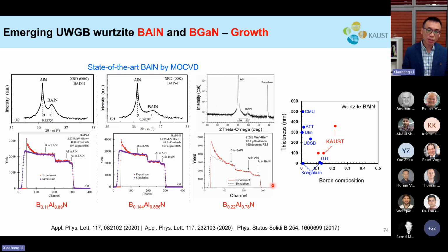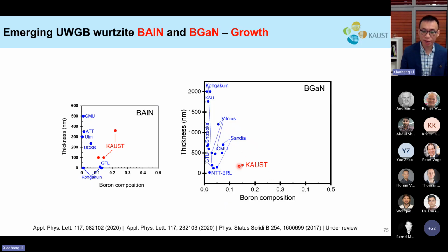So this is BAlN. How about BGaN? So for BGaN, we have developed the highest boron composition in BGaN today. It's about 15%. Okay, and we are still trying to push the composition higher so that we can measure and study the material science part of this emerging material.